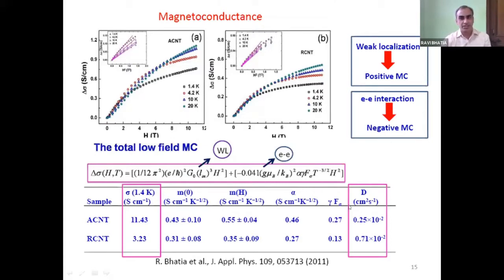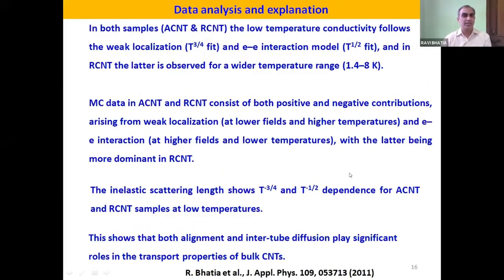However, there is a change in the diffusive properties of the charge carriers. In the aligned sample, it is much smaller than in the case of the random sample. So I would just summarize this part: if the multi-walled carbon nanotube sample is taken in aligned or randomized state, both are going to give almost similar behavior, and it lies in the metallic regime, and it does not follow the VRH conduction clearly.